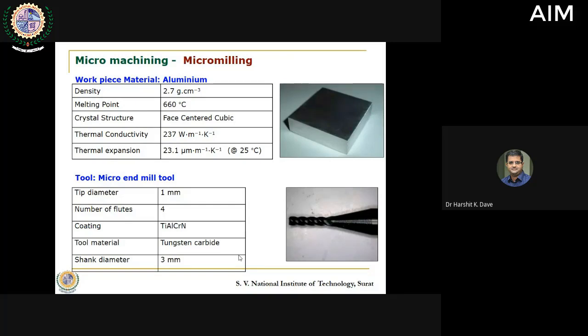We used a micro end mill tool where the tip diameter was 1 mm. At that point of time, we did not have a 0.5 mm tool. So we used the 1 mm tool to generate the micro feature in the domain starting from 25 microns to slightly larger size. This was a tungsten carbide tool material which was coated with a titanium, aluminium, chromium based coating material. The shank diameter was as usual 3 mm.